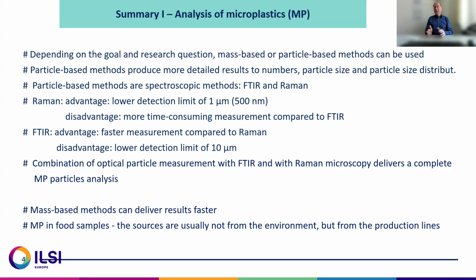So the best way would be a combination of optical particle measurement with FTIR and with Raman, and then you have a complete analysis. Mass-based methods like pyrolysis can deliver results faster. However, for the quantification, you always need a good calibration. A good message is that for microplastic in food samples, I have shown some examples, the sources are usually not so much from the environment, but mostly from the production lines.